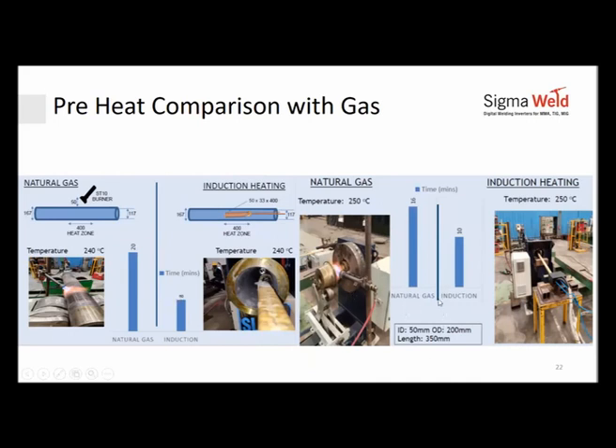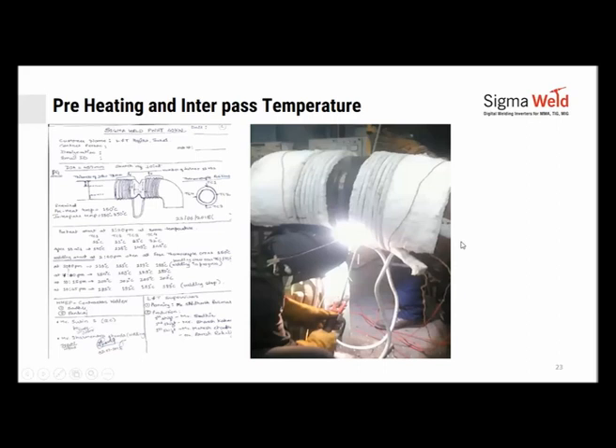Again, if you look at the OD, here is a very heavy, thick component being preheated. So again, with gas, it took about 16 minutes to bring up the temperatures on the surface. No way to measure it on the inside. However, here, since the heating is happening from inside, when you measure on the surface, it's ensured that the heating inside is equivalent or above the temperature. Again, assured much lesser time, much better accuracy of heating.